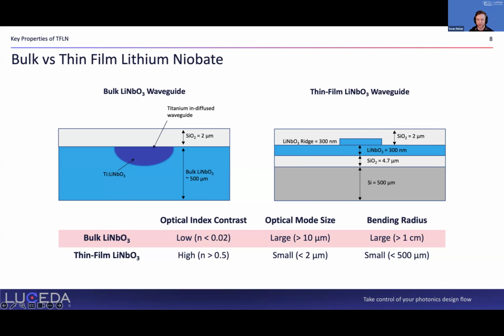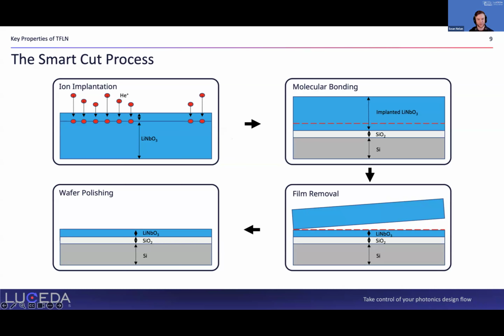So what is the smart cut process, and how is thin film lithium niobate made? The first step is we start with a bulk lithium niobate wafer. This is again that 500 micron to 1,000 micron thick wafer, and we implant helium ions into it at a certain depth. These helium ions create what's called a damaged layer in the lithium niobate, such that when we molecularly bond that lithium niobate on the top right to a silicon wafer, we can crack off the top of that film. And it cracks off at that damaged layer, leaving that thin film of lithium niobate behind.